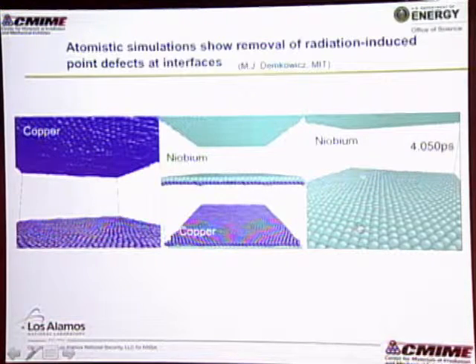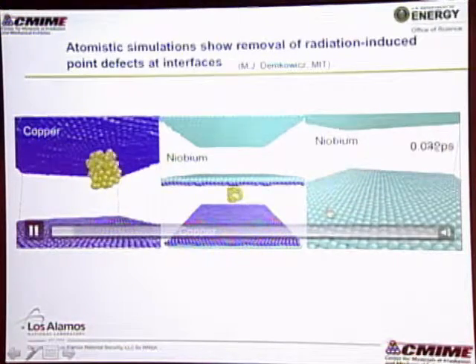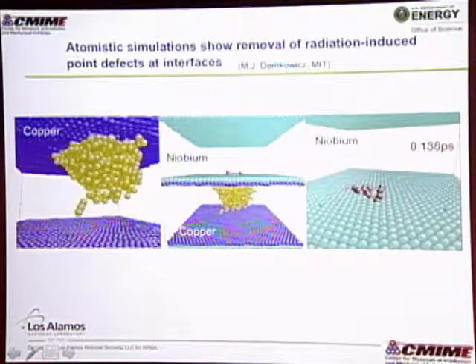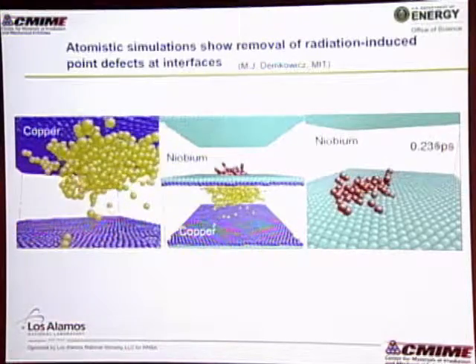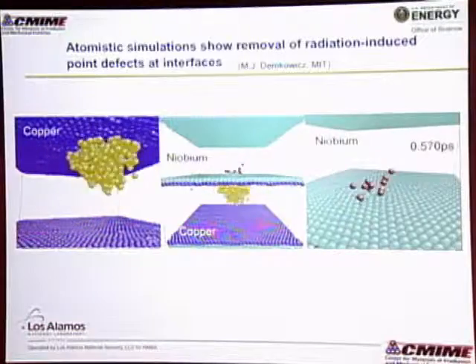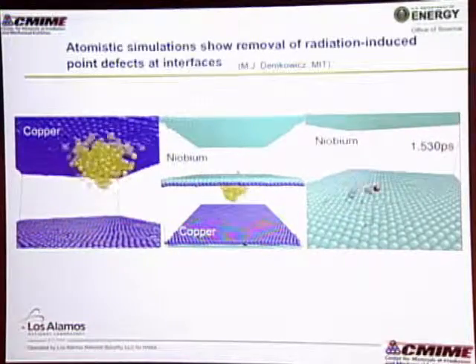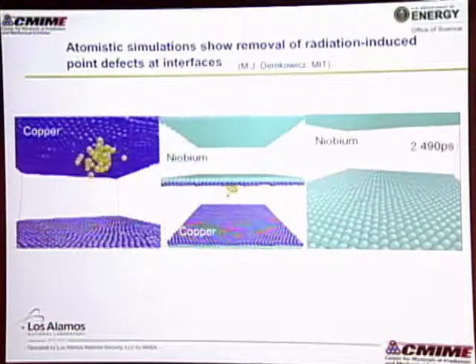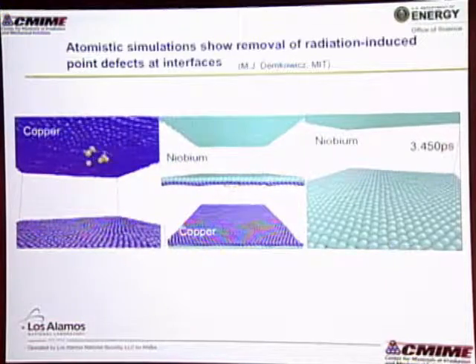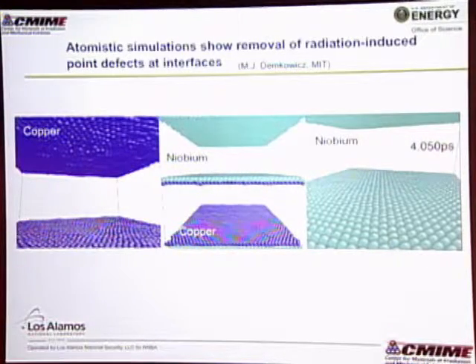This is actually a shot here of what's going to happen in the niobium, and then this here is sort of a bottom view into the copper material. We'll show it again here. So what you see is that we have this cascade form in the copper. Atoms are moving around. They're not in their happy positions at this point. Same thing in the niobium. And after only a couple of picoseconds, all of the atoms have returned to where they were initially. That is, there are no residual defects afterwards. This material just healed itself.